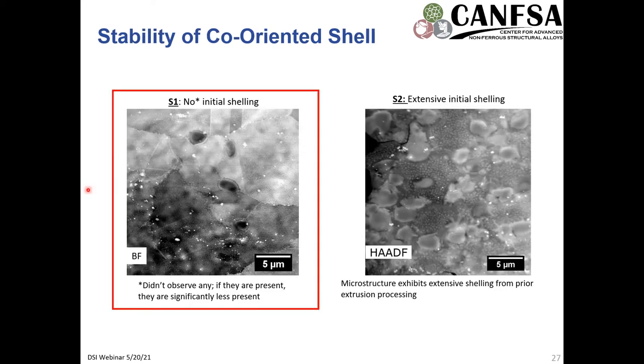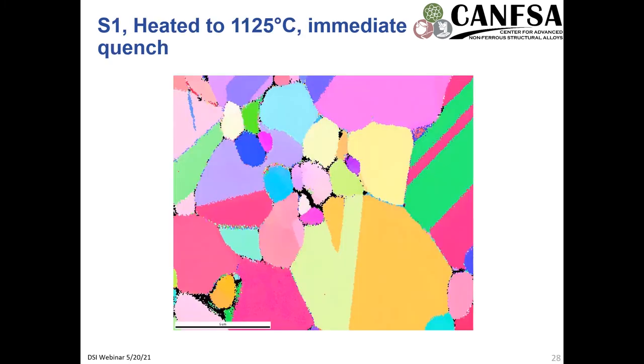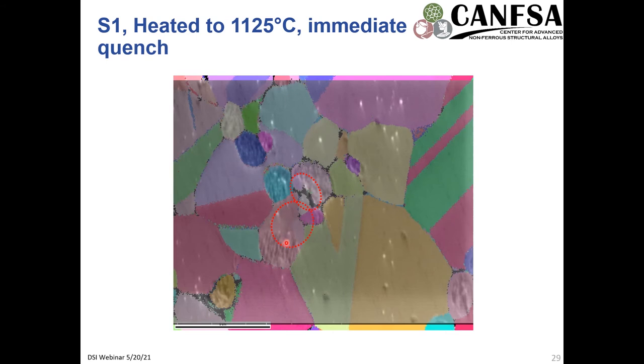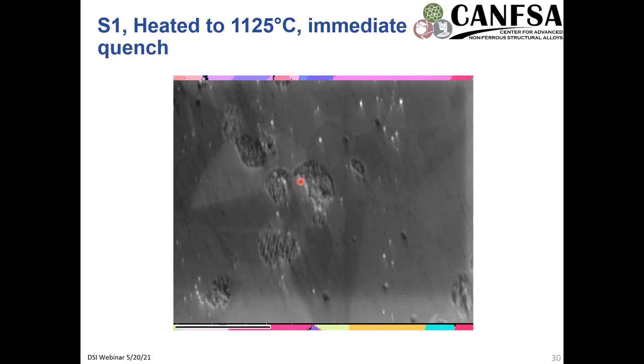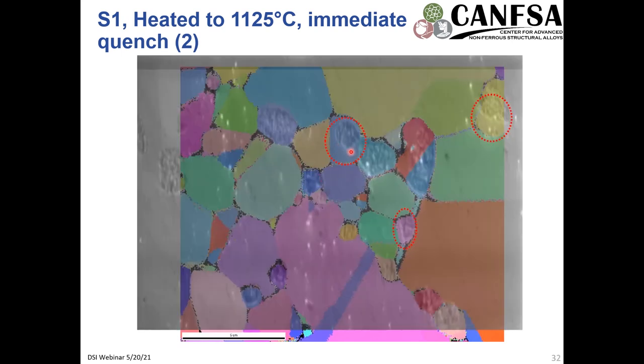So initially what we were looking at was taking a material such as what I'm calling S1, or the slice one that we received, was labeled. And this didn't exhibit any initial shelling. So we wanted to expose this to an increasing temperature and then perform a quenching operation to see if the shelling is stable. And here we have a high magnification EBSD micrograph of the region. And if we overlay the SEM backscatter and secondary electron imaging on this, we see this region here that is the primary gamma prime, and we have this adjacent gamma that has formed from the dissolution of the primary gamma prime, and this exists in this region as well. And we'll show here, particularly right here, and as well right here. And in the second example here, we have this region right there as well, and right here.